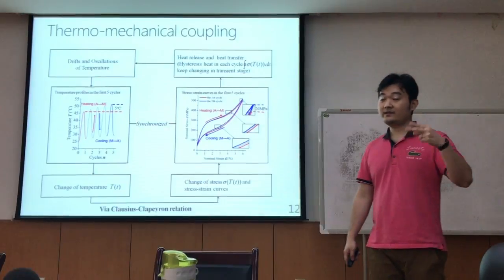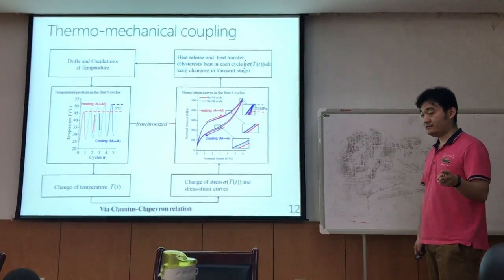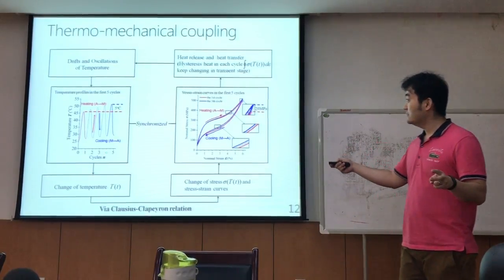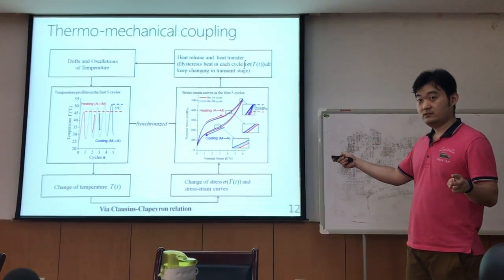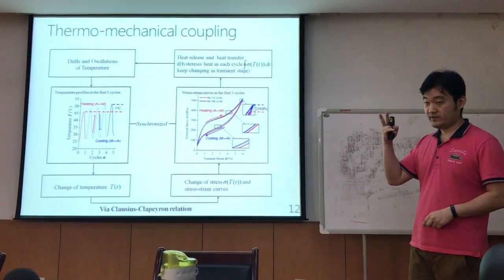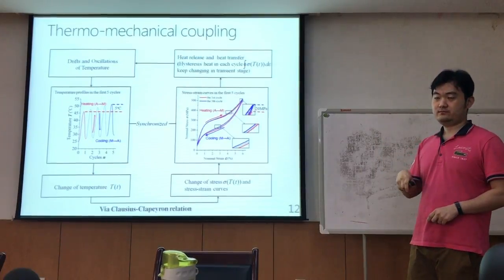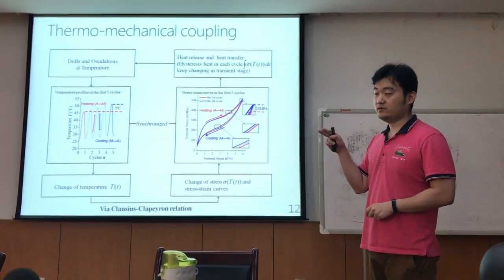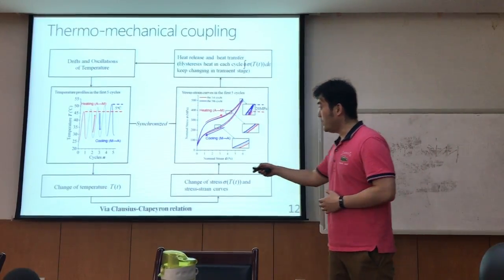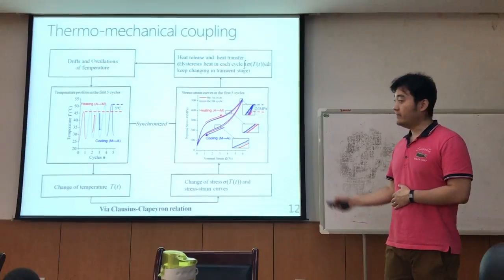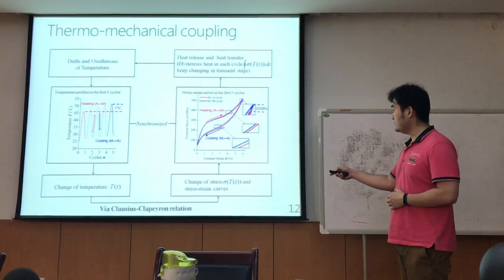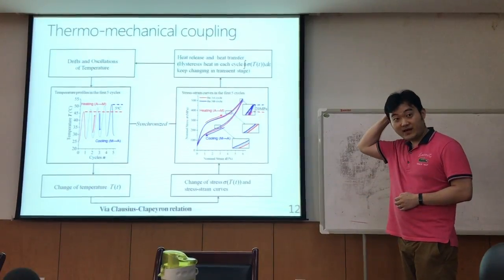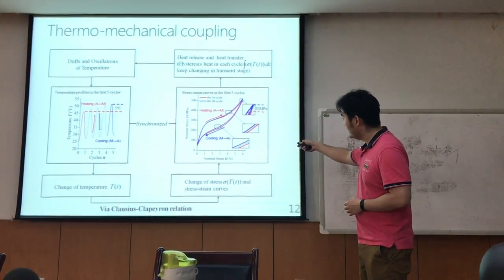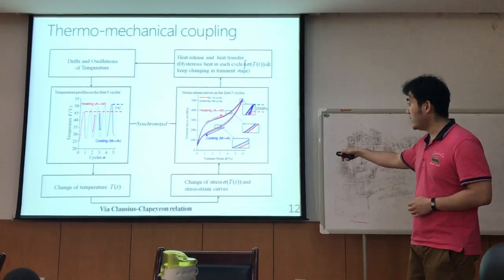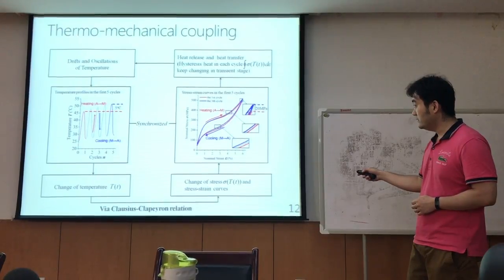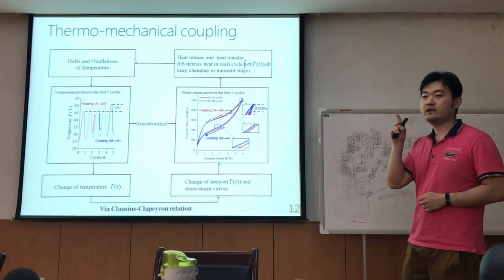So, the thermomechanical coupling. What is that? As I told you, during the cyclic loading, two heat sources, the latent heat and hysteresis heat, will be released and absorbed. This may cause temperature increase and drop. And this temperature variation will lead to stress strain variation. At the same time, the stress strain variation changes the area surrounded by the curve itself. And this area is what we call hysteresis heat, one of the important heat sources.